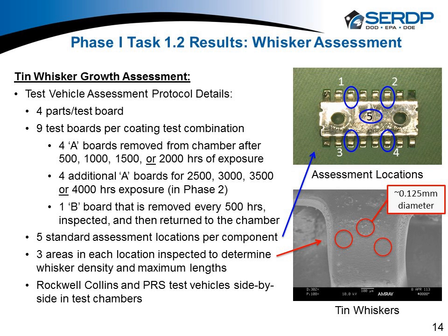And you can see here we had five different measurement areas. Four of these measurement areas are on the lead bends, which is where you tend to see whiskers. And then we also measured area 5, which is out on a flat. In phase 2, we actually quit looking at area number 5 here, mainly because no whiskers were growing.